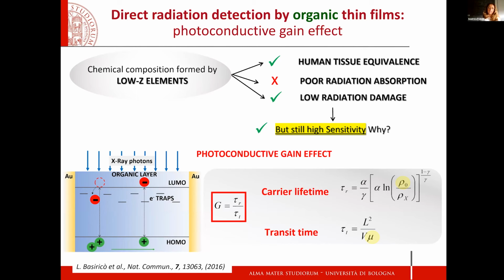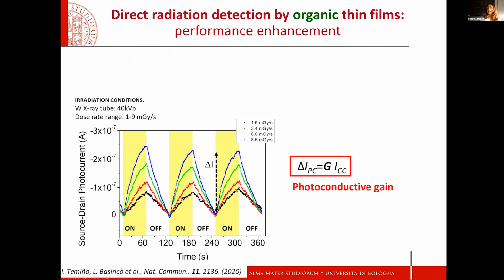So the photo-generated carriers get partly trapped at defects that have to be present in a controlled way. And there comes the strong knowledge and skills on the material, because in this way, by properly tailoring the defective states, one can modify the carrier lifetime and the transit time in the device, and therefore act on this G factor, which is the gain. This gain has a very important role in enhancing the delta I, which is the photocurrent induced after or during